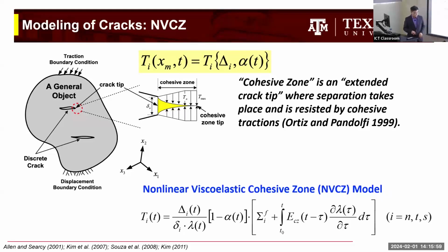David Allen. And the good thing about this model is we have viscoelasticity, so that represents virgin material, the entire process. We have a damage evolution law that simulates progression of the cracking. We have initiation criteria for crack initiation, termination criteria, length scale, and then cohesive zone strain lambda. So it's a nice T-delta relationship with other components coming together and contributing to the fracture initiation and propagation nicely.